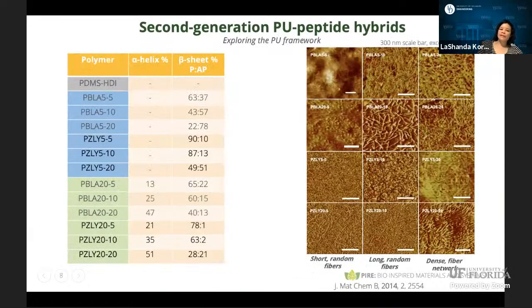We then used ATR-FTIR to look at secondary structure in these material systems. So as anticipated, based on what we know from literature about the peptide structures and their impact of block length on secondary structure, for both the PBLA and the lysine systems with a block length of 5, regardless of the composition, you had all beta sheet structures. What does change is the balance between parallel and anti-parallel beta sheets. Now, I will say the anti-parallel beta sheet structure is the most thermodynamically stable.